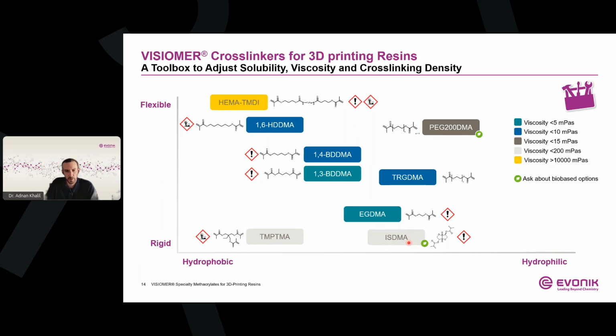This again allows the formulators to tune the balance between flexibility and stiffness according to the targeted end application. At the same time, the portfolio also spans a wide hydrophobicity and hydrophilicity range. So more hydrophobic crosslinkers can support moisture resistance and dimensional stability, whereas more hydrophilic structures may improve the compatibility with other polar formulation components. Another important aspect is the viscosity, as shown again by the color coding. So the products cover a broad viscosity range, enabling the formulators to optimize their processing while retaining the desired level of crosslinking.